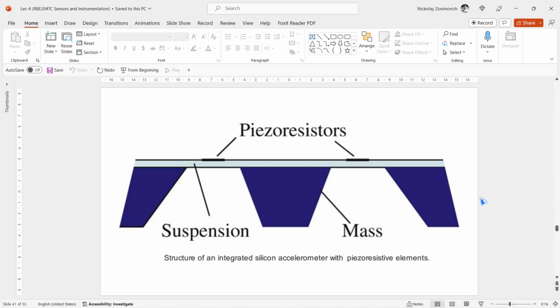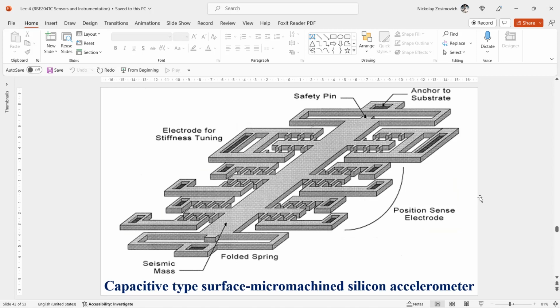Since the device is sensitive to inertial forces, it can be packed in a hermetically closed housing, making it resistant against mechanical and chemical influences from the environment. Silicon accelerometers with micro-machined mass, spring, and integrated piezoresistors feature a high resonance frequency, up to 550 kilohertz, and small dimensions and weight, up to 0.4 grams, and low cost. They are available with 1, 2, or even 3 sensitive axes. Usually they can be mounted on a suitable spot on a mechatronic construction, and they furnish useful information on position, orientation, and rotation of mobile parts.